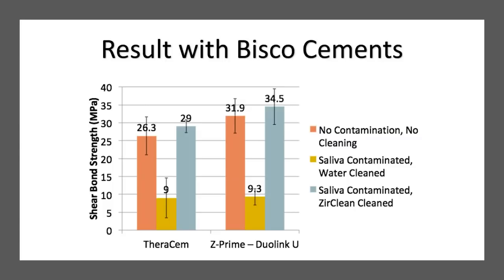It's interesting because if you look, Z Prime, which is a zirconia primer, and this is one of the questions I ask on the quiz later, Z Prime is not indicated in every cement for zirconia. With Theracem, you do not need to prime the inside of the crown. You clean it with Zirclean or IvoClean, rinse and dry, and then you cement. With Duolink, because it doesn't have MDP, it needs to have a primer internally. So you must know your cements and what they recommend.